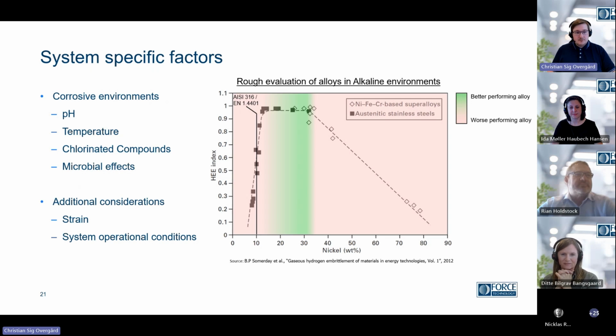This is not even to touch on system-specific factors, where the picture becomes even more complex. Effects such as pH, temperature, the presence of chlorinated compounds, certain microbial effects, and even the pressure of the hydrogen you're working with have an effect. As an example, in the figure on the right, you can see a rough evaluation of nickel-containing alloys in a high temperature and highly alkaline environment under the presence of several bars of hydrogen pressure. In this case, you want a higher nickel content to increase the corrosion resistance in the alkaline environment. However, as your nickel content increases, so does your susceptibility to hydrogen embrittlement. So there's a small Goldilocks zone where you maximize your corrosion resistance and minimize the risk of hydrogen embrittlement.